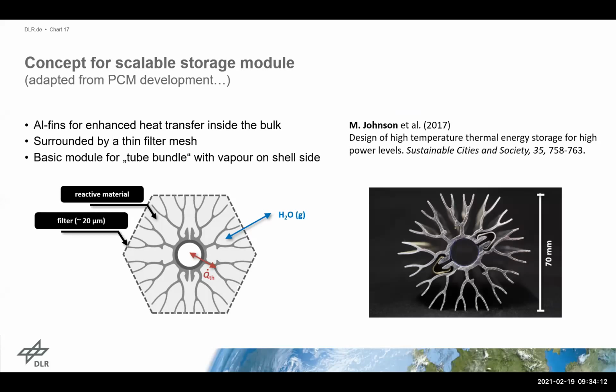And I mentioned it in the introduction that our colleagues, for instance, from the PCM group, have developed this fin structure you see on this picture. They use it now in kilometers length. The idea is that we have a stainless steel tube inside. The stainless steel is able to withstand some pressures we need for evaporation or condensation of water, for instance. We have aluminum fins, of course, to distribute the thermal energy into the bulk. And we have these clamps that actually connect these two parts of this heat exchanger or heat transfer measure.